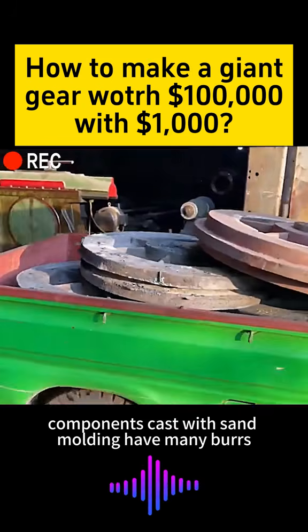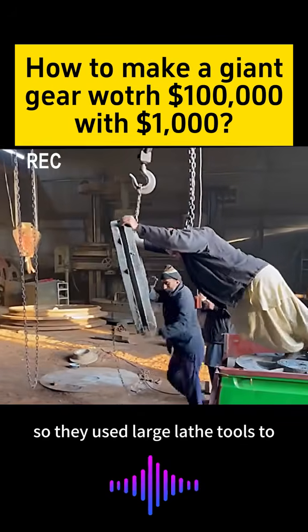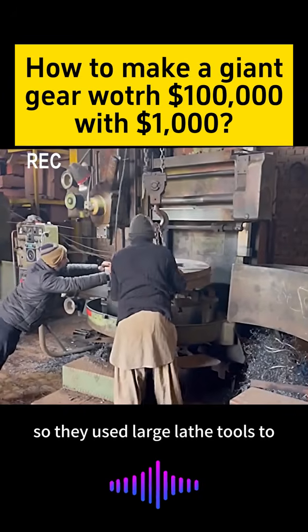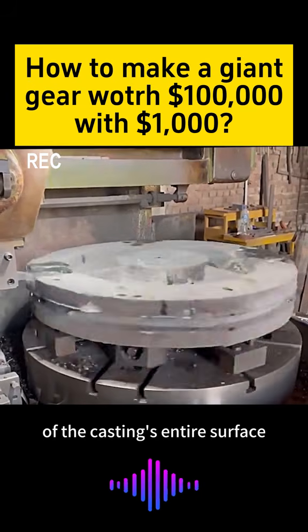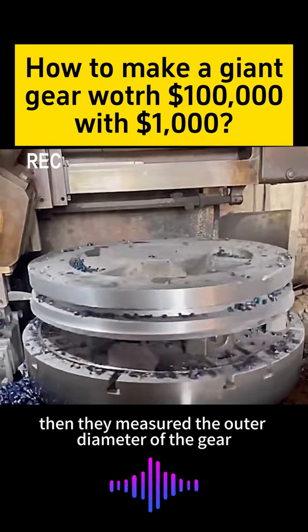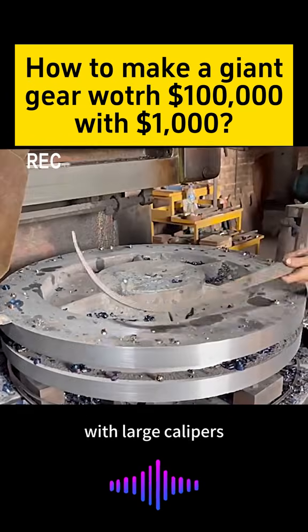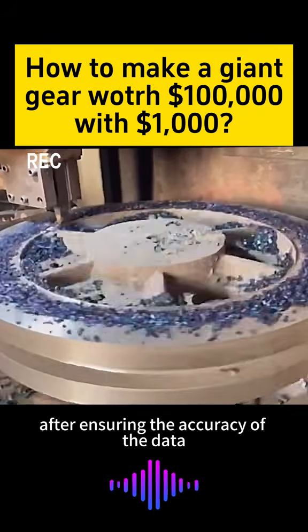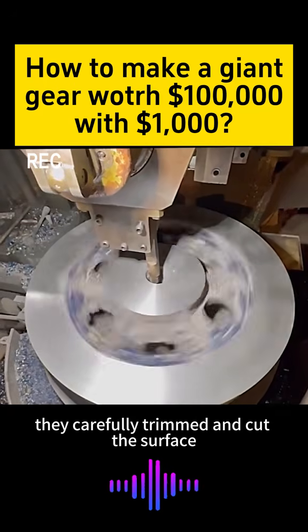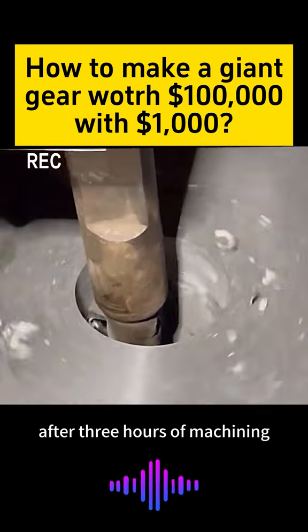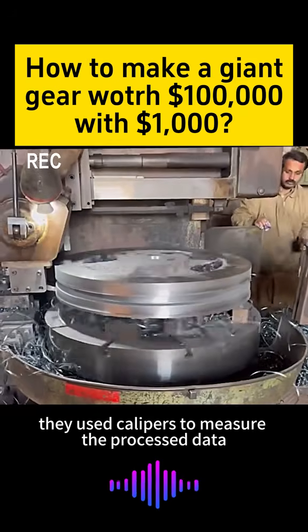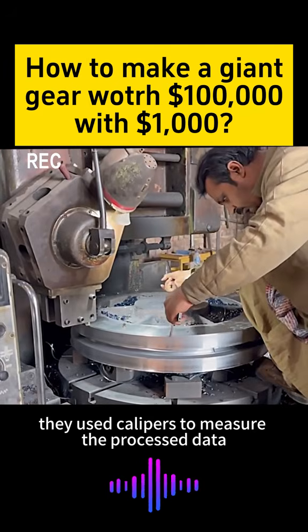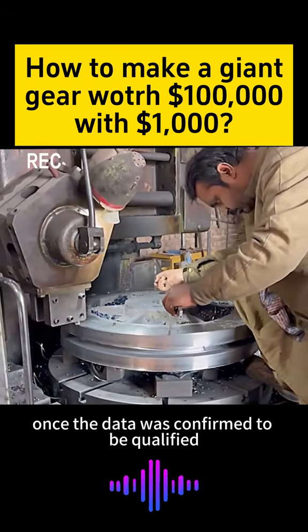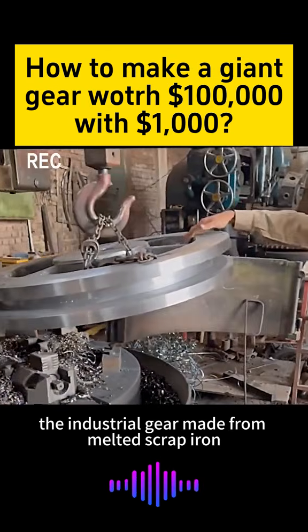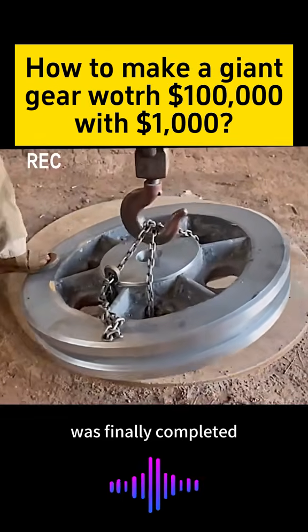Components cast with sand molding have many burrs, so they used large lathe tools to completely cut off a layer of the casting's entire surface. Then, they measured the outer diameter of the gear with large calipers. After ensuring the accuracy of the data, they carefully trimmed and cut the surface. After 3 hours of machining, they used calipers to measure the processed data. Once the data was confirmed to be qualified, the industrial gear made from melted scrap iron was finally completed.